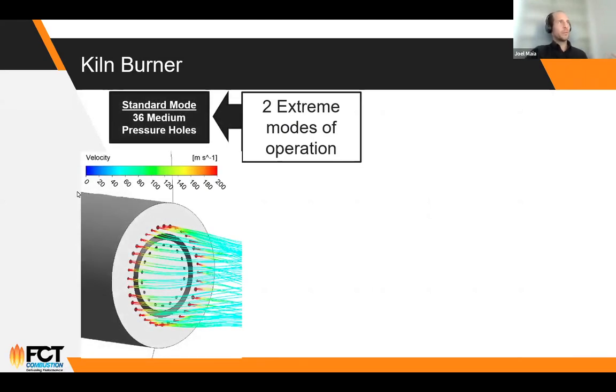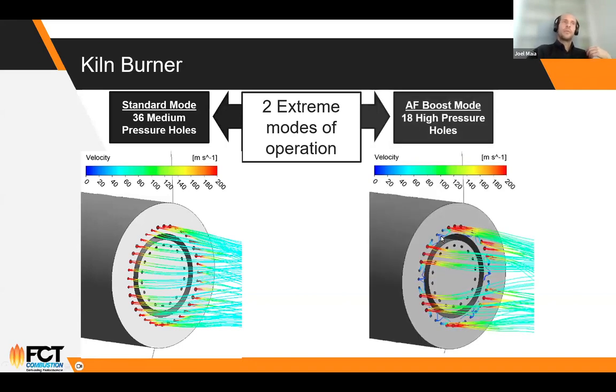One mode would be what we call standard mode, in which we have air being supplied through all axial air orifices. This generates a milder flame, not so intense, suitable for operation with traditional fuels, for example. And then, closing a valve outside the burner, you don't stop, you reduce to a minimum, because you can see here that you still supply a little bit of air for cooling and to avoid clogging. But for process purposes, this amount of air is very small.